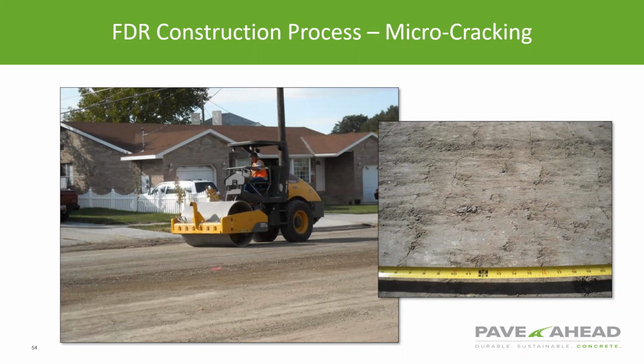I said, "I have an idea." I wasn't out here for the last little bit of the job, so I called the foreman on speakerphone. The job required like 35 ton of cement or something like that, some odd number, so it was like a partial load. Of course, we ordered what we needed, but an extra 5 tons showed up. We didn't realize the extra 5 tons showed up until after the fact. It's already in the spreader truck, the pneumatic tanker's down the road, and we've already blended in 3/4 of the job. So we had no other place to use the cement, and they just put it on that last little bit of the road.